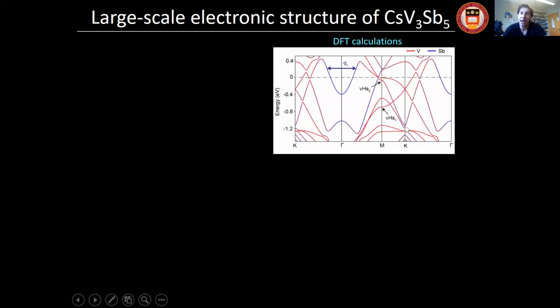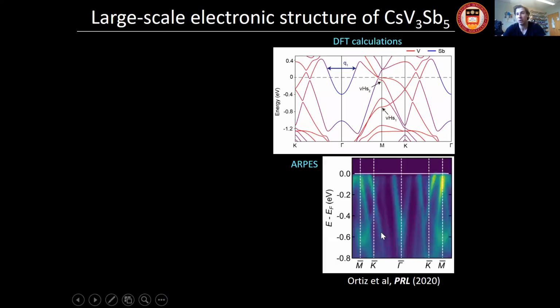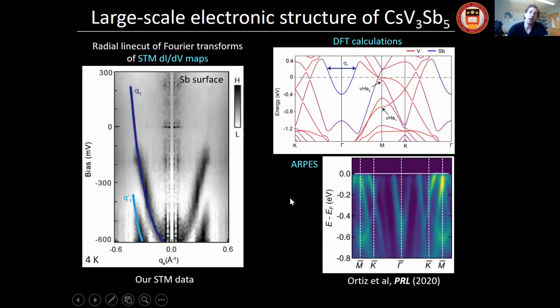The first thing we wanted to check is, using STM, to what extent can we access the true electronic structure of CVS. For that, we performed DFT calculations in collaboration with our theory friends. We don't do that in my lab in particular. We then compared to ARPES as well. DFT calculations actually match the ARPES fairly well, so we just wanted to see to what extent the STM will be able to match them as well. So we use QPI measurements, as we generally refer to them.